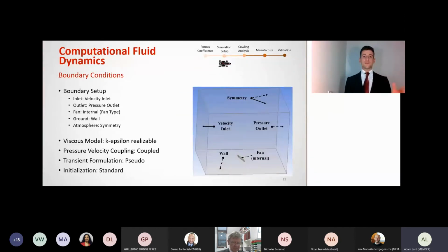The first step in creating the fluid simulation was setting up the correct boundary conditions and viscous model. Through the literature study, it was determined that the K-epsilon realizable model was in fact the most suitable for this application. It is often presented as the default model setting in many commercial software packages, and after importing this model into ANSYS Fluent, the radiator could then be defined as the porous zone. And it was at this point that the coefficients obtained previously could be input for the relevant direction vector of the flow.